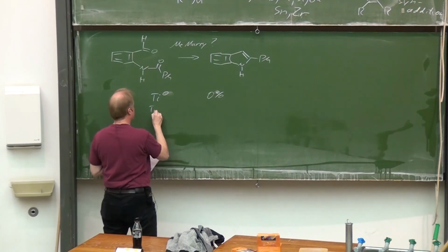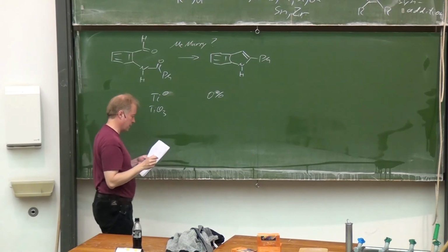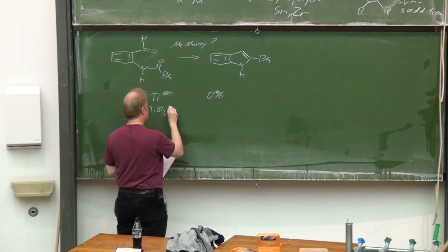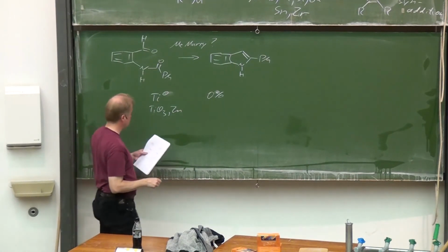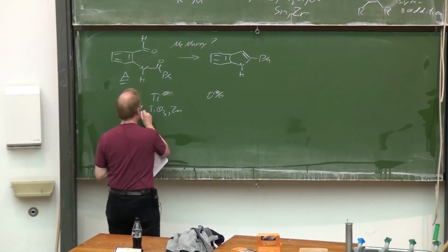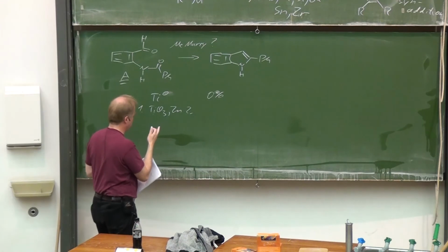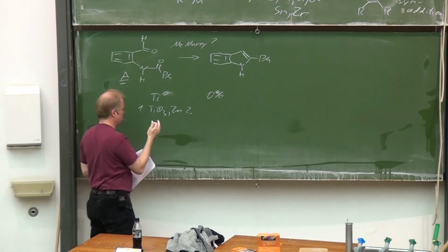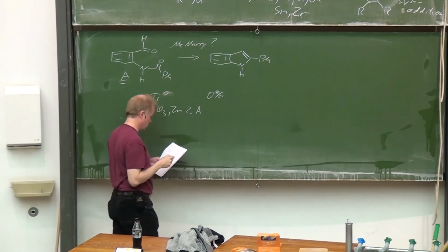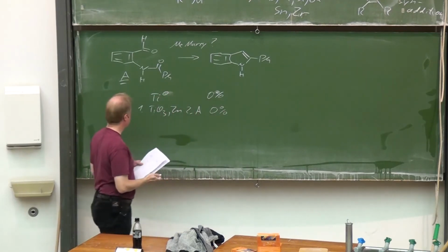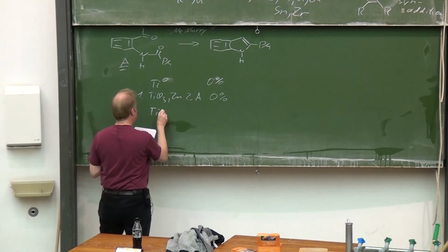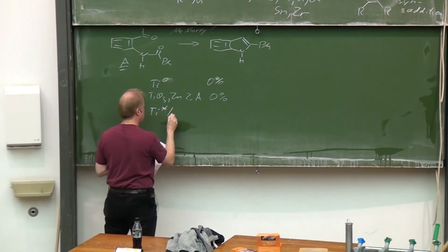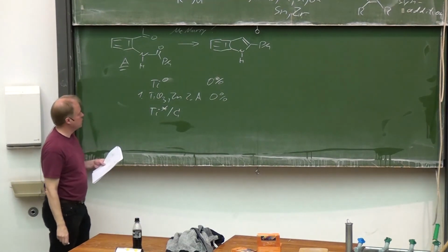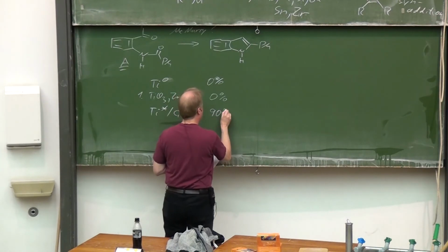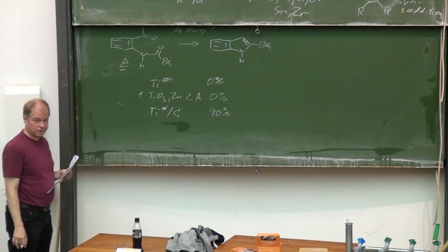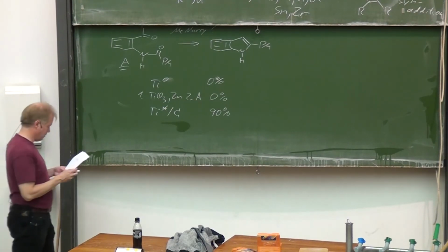Then, the second attempt was titanium 3 chloride plus zinc, and this is substrate A. Secondly, after the formation of the reduced titanium species in solution, the substrate A was added, and again 0% yield. Then, with Fürstner's highly active titanium on graphite, it worked very well with a 90% yield. But he found an even better method.